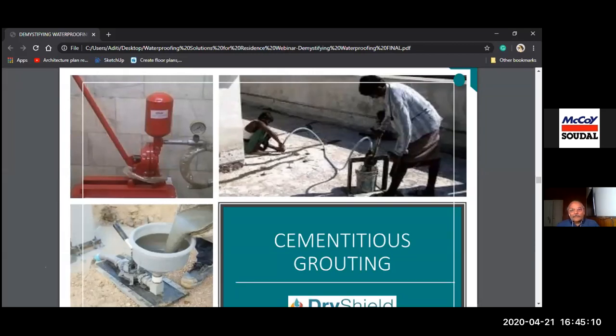Now, just imagine on a 50 kg bag of cement and 100 grams of admixture, how would someone mix it properly so that it gets dispersed in the entire powder and becomes part of the entire 50 kg cement? The chances are less. That's why when something like this is done in concrete for repairs, some areas still have leakages, because wherever the admixture and cement has gone, that area will get treated, and where only cement has gone, the slurry will shrink and it will become useless. While if you see the machine on the bottom left, which is the electric pump, this is used to grout a cementitious product which is factory made, a product which has all the admixture added to it.